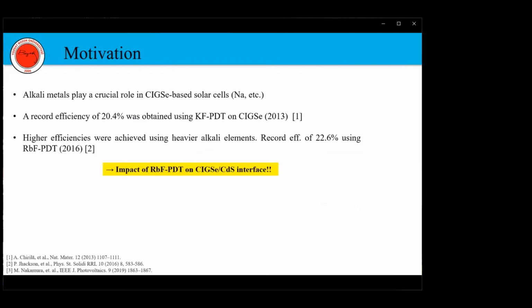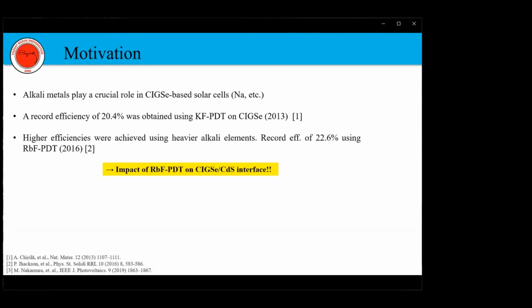In addition, it is well known that alkali metals play a crucial role in CIGS-based thin film solar cells. In 2013, a record efficiency of around 20% was obtained using potassium fluoride post-deposition treatment, whereas in 2016, an even higher efficiency of more than 22% was achieved using rubidium fluoride post-deposition treatment. Therefore, our second motivation is to investigate the impact of rubidium fluoride post-deposition treatment on the CIGS/cadmium sulfide interface.